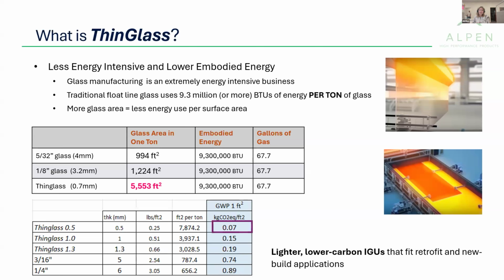Thin glass is also less energy intensive and has lower embodied energy than traditional glass by virtue of how many sheets of glass that we can produce out of a single ton. So a traditional float line uses about 9.3 million BTUs of energy per ton that it manufactures. 1 ton of, say, 1/8 inch residential glass can produce about 1,225 square feet. With that same ton of glass at 9.3 million BTUs, we can produce over 5,000 square feet of thin glass. So once we amortize the energy usage across how many sheets of glass that we can produce, we're dropping our GWP, or global warming potential, per square foot of glass, cutting that in half or more. So the result is that with thin glass, we can make lighter, lower carbon insulated glass units that both fit retrofit and new construction.